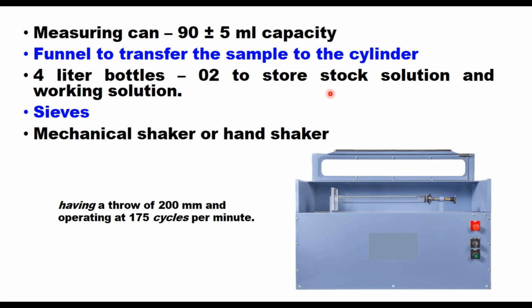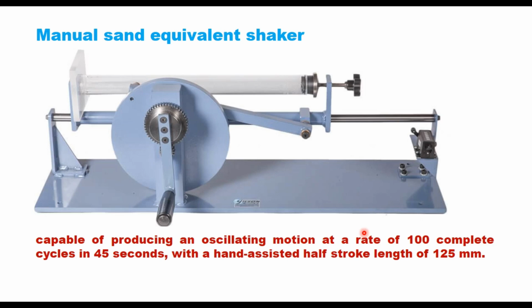2 4-liter bottles to stock a solution and working solution as I showed you in the siphon assembly, then a sieve and a shaker. Now this shaker can be of mechanical type like this, or it can be a hand shaker also. In case of a mechanical shaker, a throw of 200 mm and an operating speed of 175 cycles per minute is required. In case of manual sand equivalent shaker, the sample is fitted here and this is rotated by hand. It should be capable of producing an oscillating motion at the rate of 100 complete cycles in 45 seconds with a hand-assisted half stroke length of 125 mm. Or it can be done by hand also.